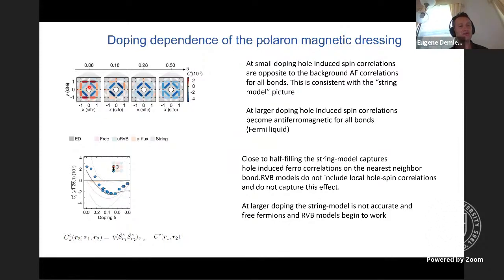Close to half filling, a hole would always introduce correlations that are opposite to what one would get in an unperturbed antiferromagnet. Say, nearest neighbor would acquire extra ferromagnetic correlations, they are positive, but this only happens next to a hole. I remind you, it's really an extra polaronic configuration, or let's say a diagonal correlation, which away from the hole was ferromagnetic. Due to the hole, they acquire a ferromagnetic component. So this is really a signature of a magnetic polaron, but then as we go to much larger doping, all the additional hole-induced correlations appear to be antiferromagnetic-like.